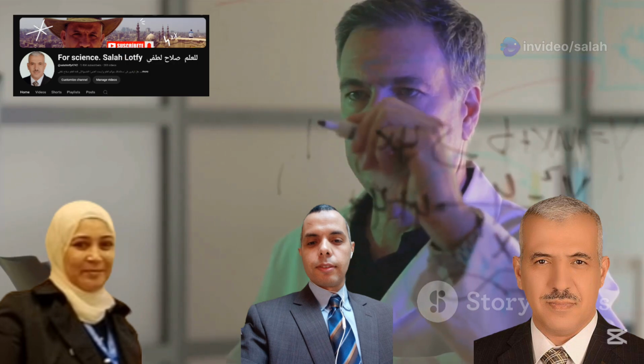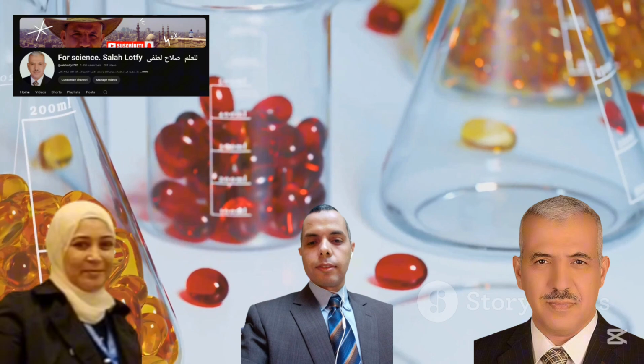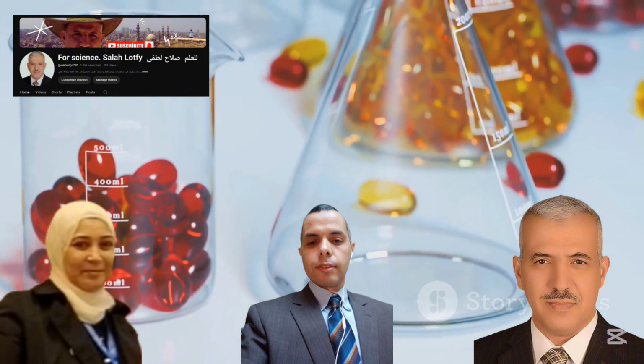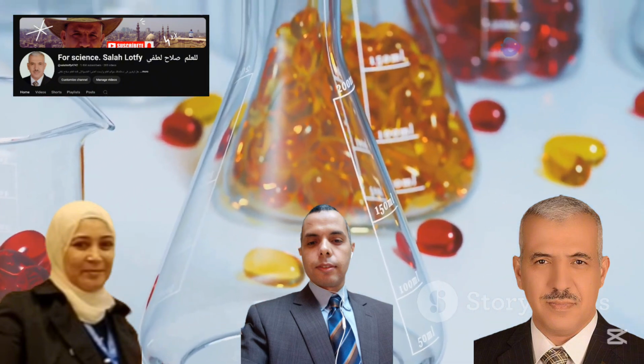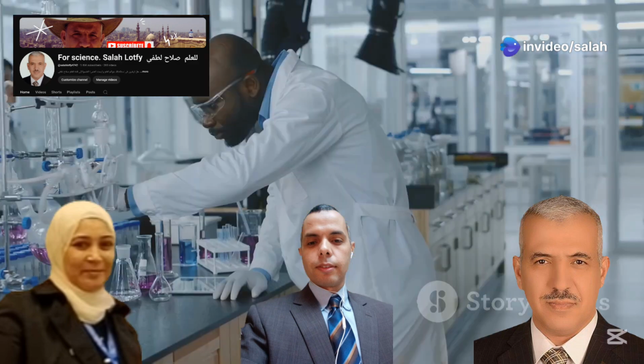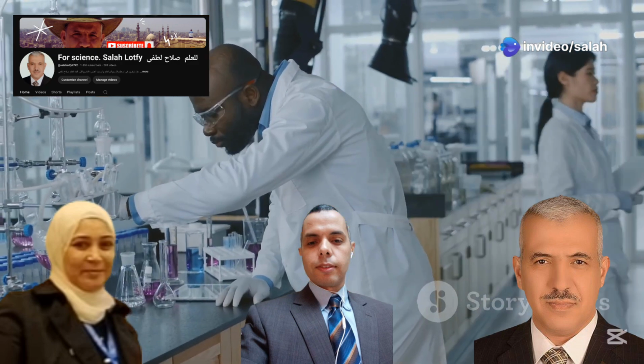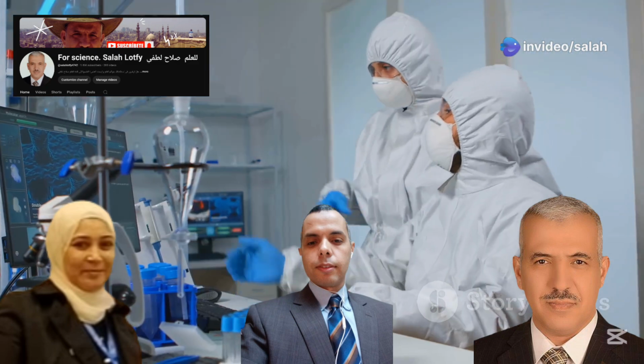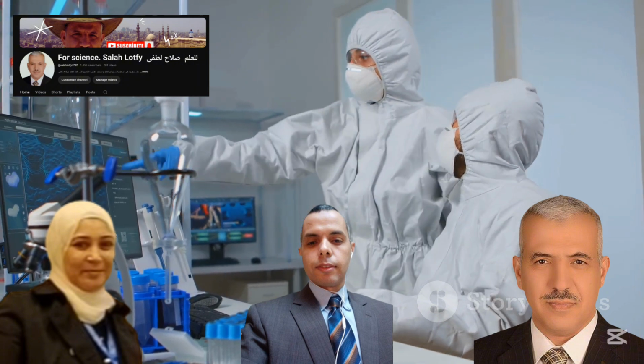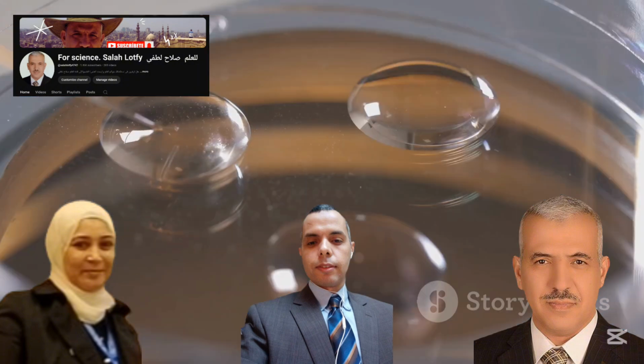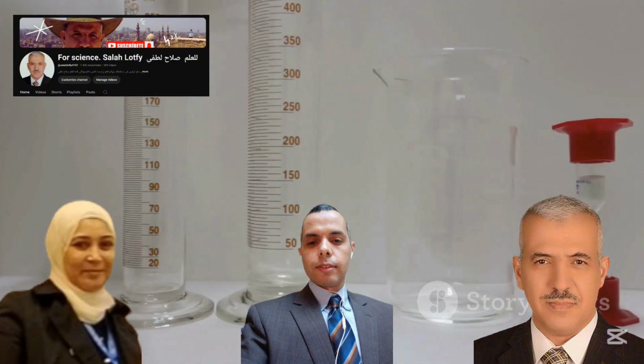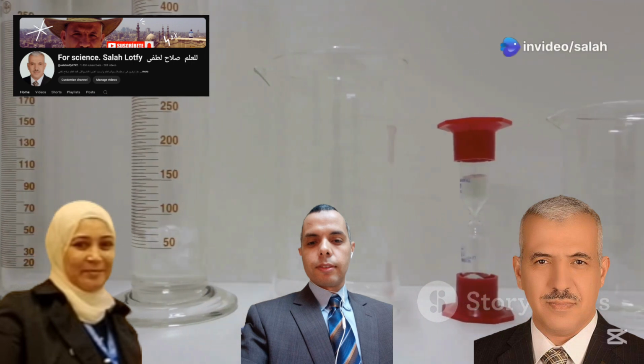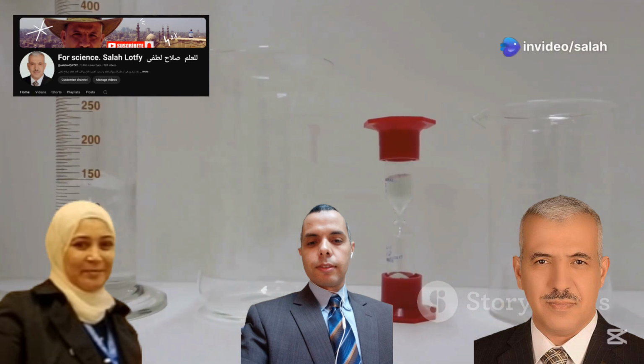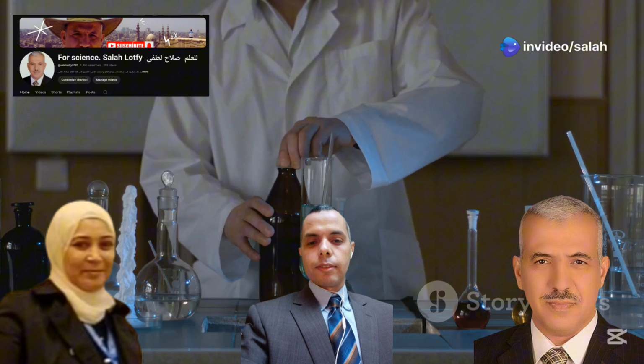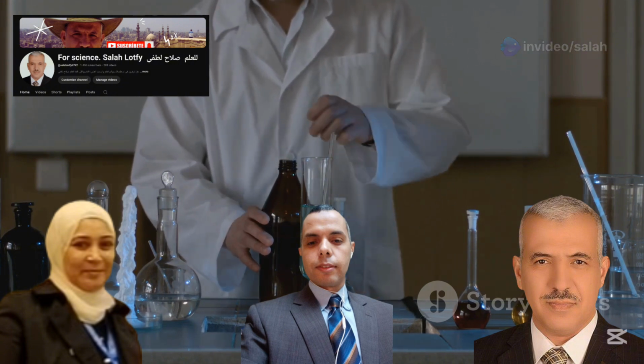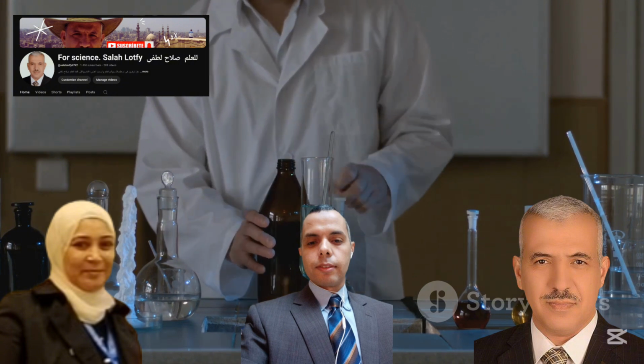So, what's this all about? These researchers are investigating superabsorbent hydrogels. Think of them as super sponges that can soak up water but leave behind ion components. They're made using gamma irradiation, which might sound like something out of a sci-fi movie, but it's actually a very controlled and precise method. Water retention is a big deal here. The team found that hydrogels made at lower irradiation doses, like 5 and 10 kGy, held the most water. That's critical when you're trying to clean up ink waste, especially in different environments like air and acidic conditions.